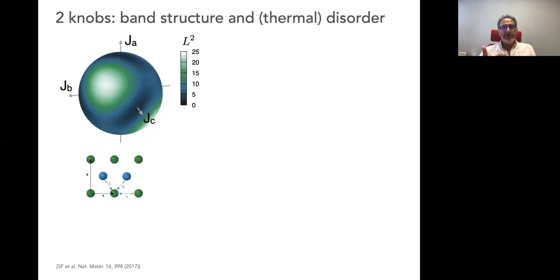One is band structure, and the other one is the amount of thermal disorder. So this is work we have done a few years ago with Alessandro Torrisi. We realized that to a good approximation, you can map almost every organic semiconductor into this simple structure with three principal transfer integrals, JA, JB, and JC. And then evaluate the localization length as a function of the band structure. And here the color code is: more localized is black, and more delocalized or more conducting is white. So you see that, for example, if you are one-dimensional, which means one of these axes is all black, performances are very poor. And if you are here on the white spot, this is the best spot. This corresponds to an isotropic material with all equal values of the transfer integrals.